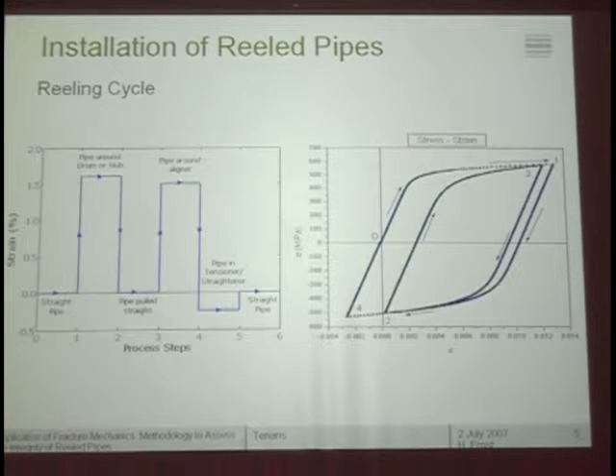Of course, if you look at a little element on the body of the pipe, the longitudinal strain that this little piece of material will see is, say, 0 first. When you put the pipe around the drum, you have a deformation of between 1.5 and 2%. Down to 0 again, you pull the pipe straight, go up to the second wheel, that is the aligner as we call it. It's a little less than 1.5, then comes down to about minus 0.1 or so to have the pipe finally straight again. If you look at the stress-strain curve of this, that will go from 0 to number 1, then to number 2, then to number 3, and then to number 4. So basically we are seeing 2 deformation cycles under normal operations that the material has to see.